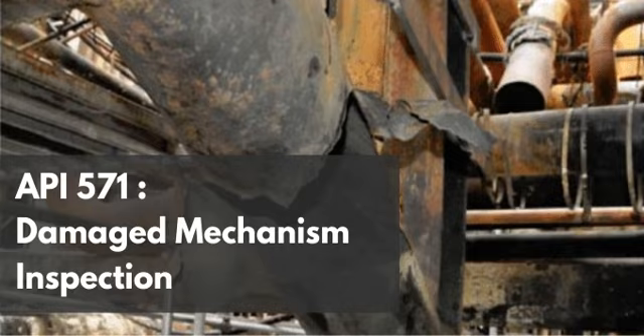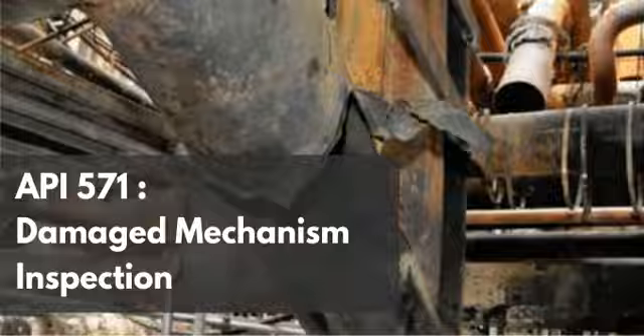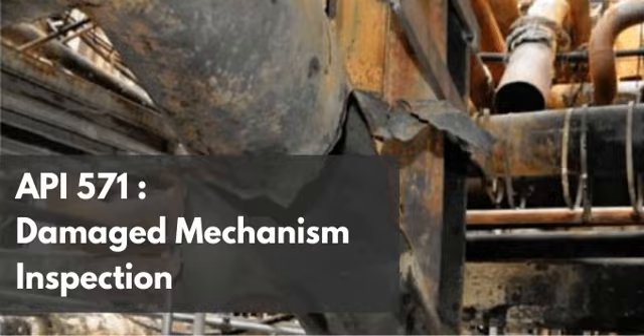Exactly. That oxide scale acts as both a chemical and a physical barrier. The gaps in that oxide fence are way too tight for the carbon atoms to slip through. So it physically blocks them. It blocks the carbon from ever reaching the bare iron matrix below. But in a highly reducing environment, meaning a chemical environment packed with hydrocarbons and virtually no oxygen, that protective oxide scale either never forms in the first place or it actually gets chemically stripped away.